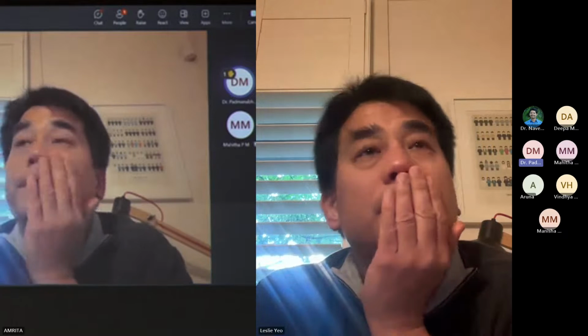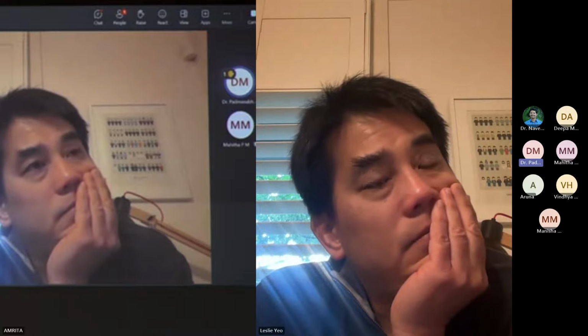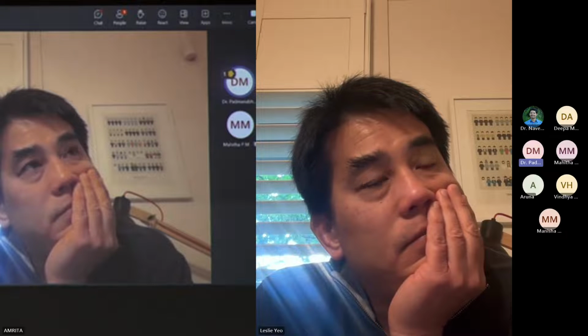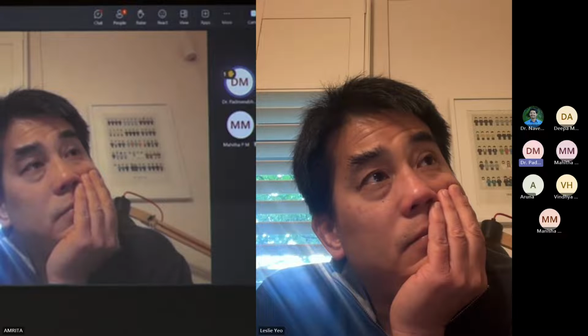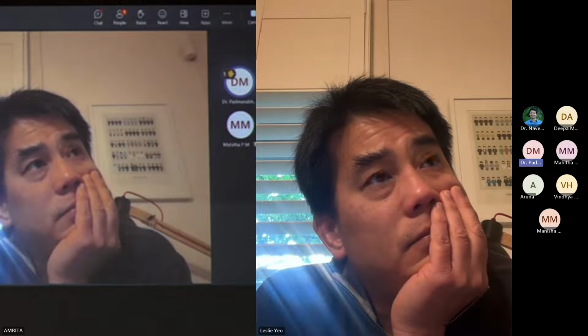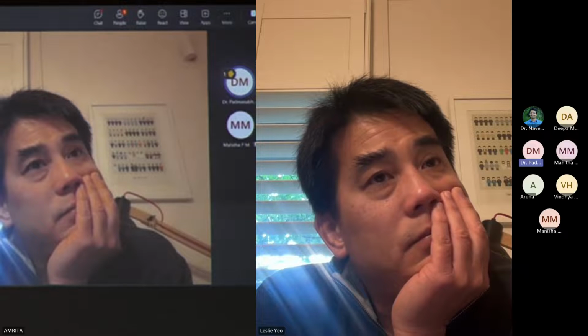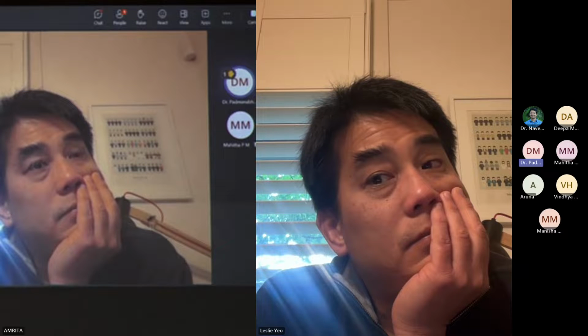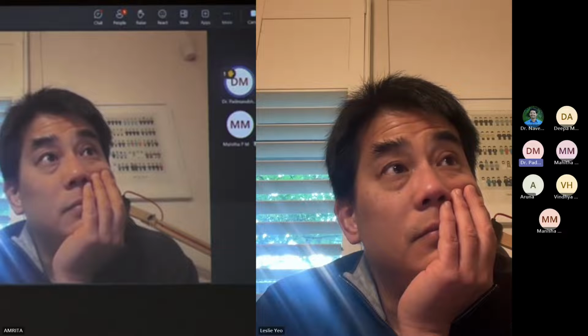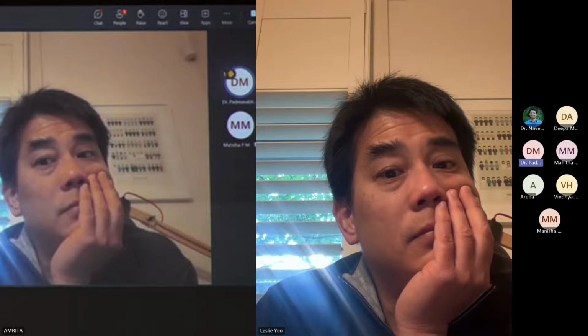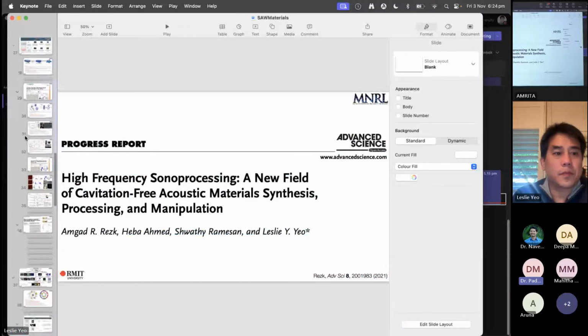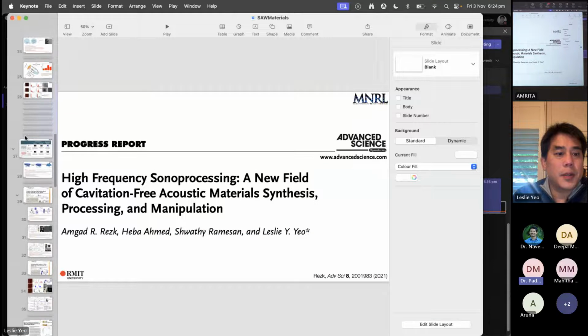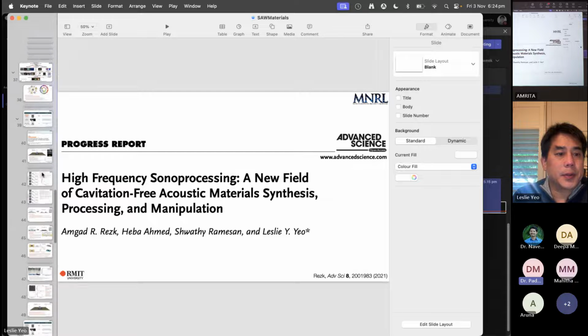But there are two small questions. One is, after doing the sonochemical treatment of HKUST, did you take a powder XRD of the material and find out whether it really matches the real HKUST? Because mostly it must be comparable to the bulk material, suggesting that the structure is really retained.